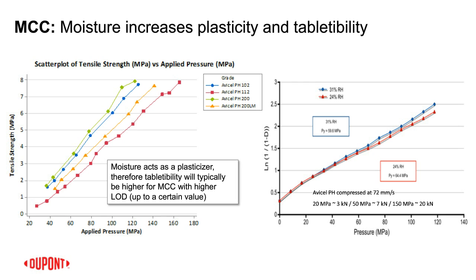Yes, sure. Actually, that's a very good question. When you test them 100% pure, so this graph is just the material MCC by itself, the surface area doesn't matter too much, right? So all the MCC is surrounded by themselves. As soon as they contact under compression, they have plenty of surface area to bond. But when you put them in formulation, that's where the difference starts to show up.